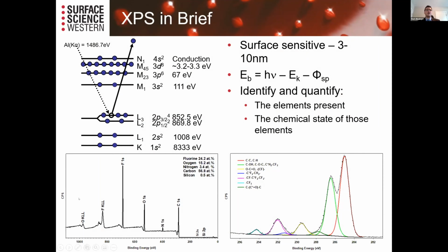So we have over here what we call a survey scan, where you use all these peaks, and the areas under these peaks in relation with relative sensitivity factors can give you how much of the different elements you have present within the material. If you zoom in on a peak, say the carbon 1s peak, that's this over here, what you call a high resolution scan, you can get the chemical state of those species. And so we have carbon bound to carbon here, and up here we have carbon triply bound to fluorine and all sorts of species in between that you can calculate how much of those that you have. So the various chemical states.